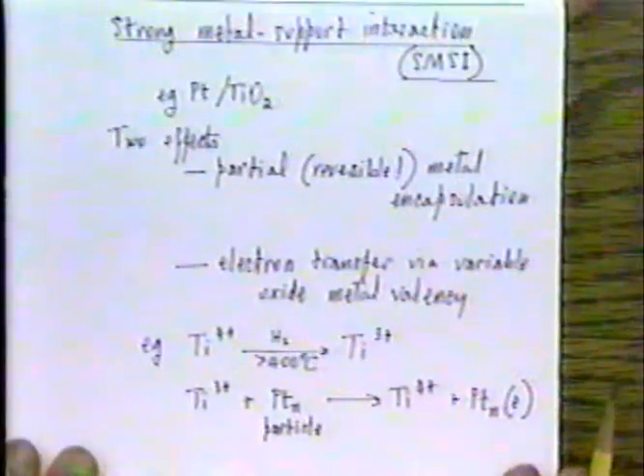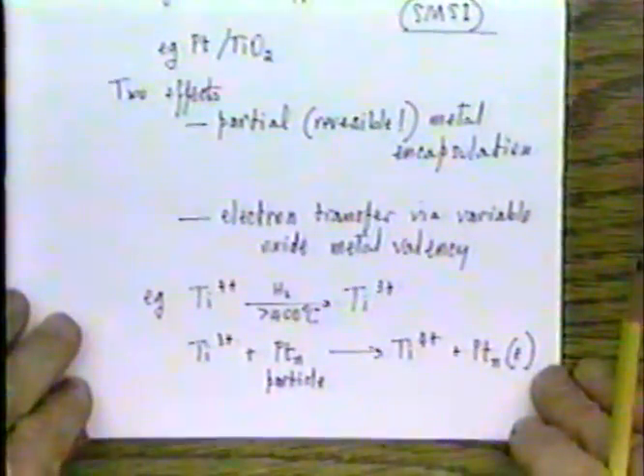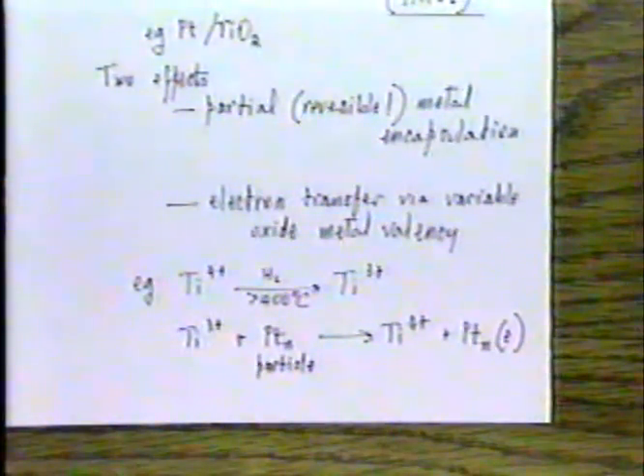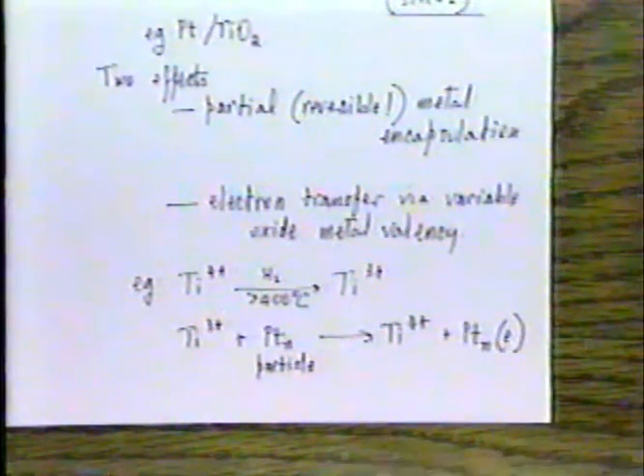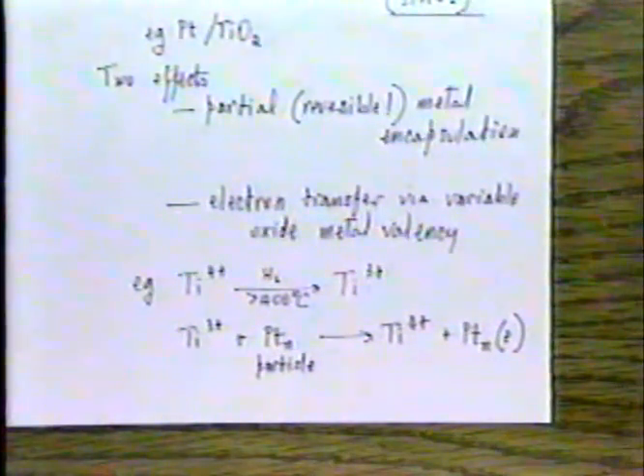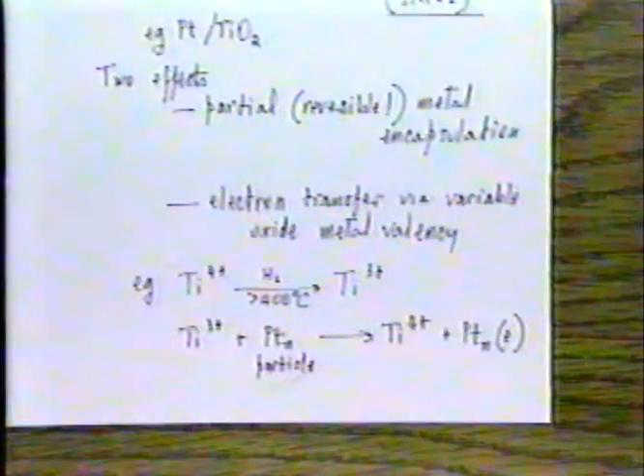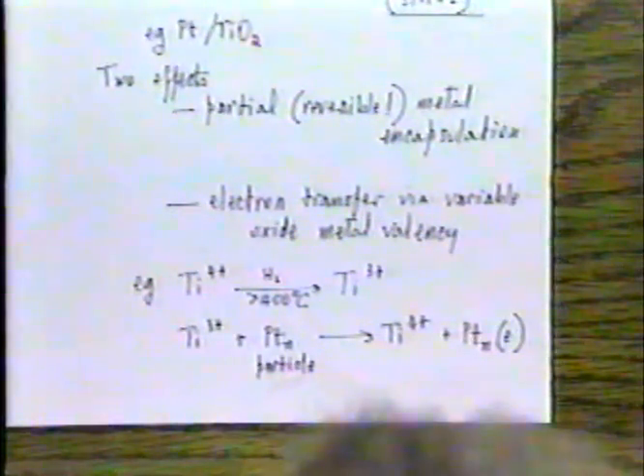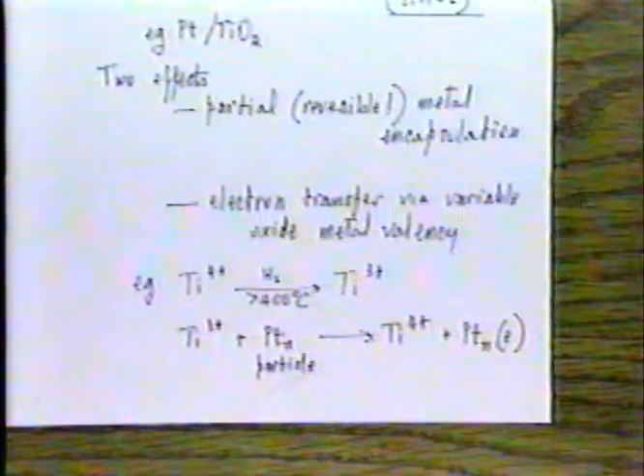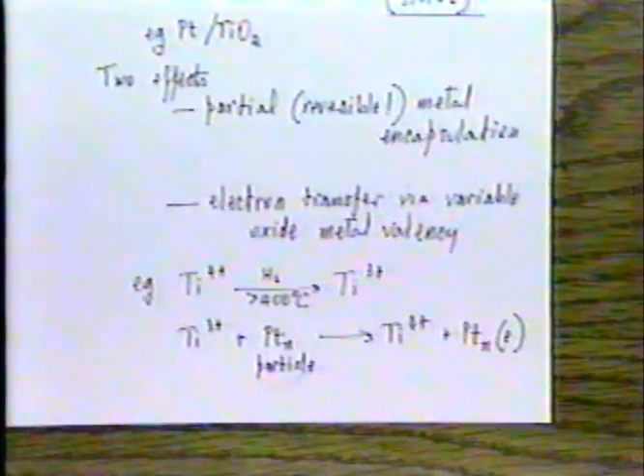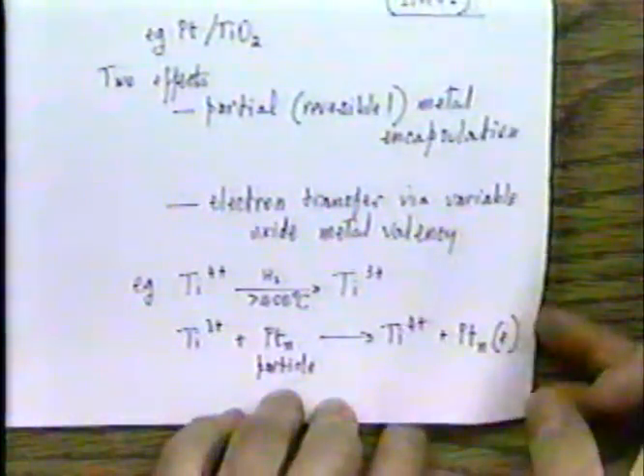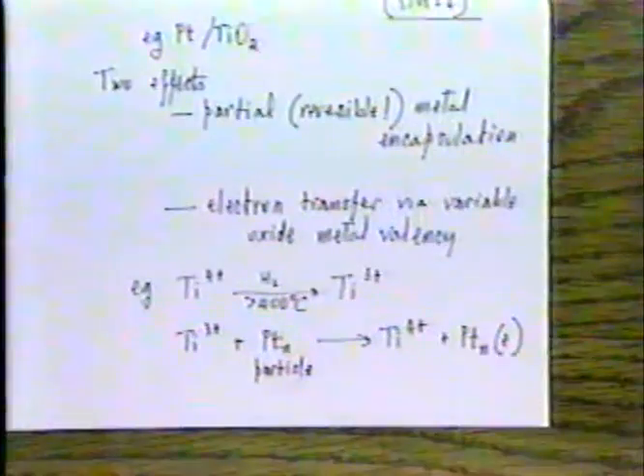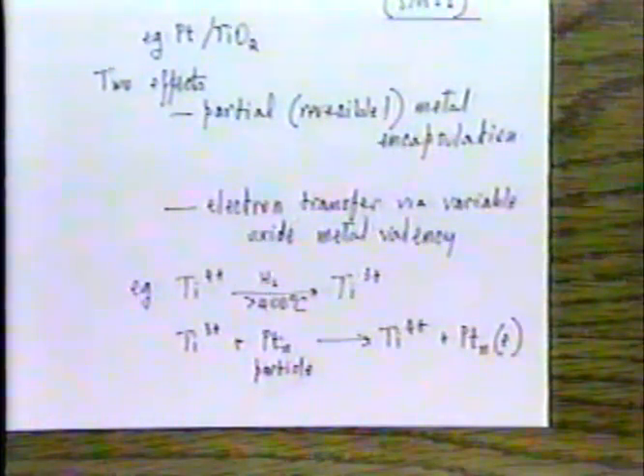However, there is very likely an actual electron transfer effect taking place at the same time, and this is summarized in those two equations at the bottom of the sheet. That is to say, under reducing conditions, some of the Ti4+ is reduced to Ti3+, and the Ti3+ functions as an electron sink in relation to the platinum particle which is sitting on the surface. In effect, it can dump an electron back into the platinum particle. The platinum particle functions as an electron-rich particle, which tends to inhibit hydrogen chemisorption, and in fact has an effect also on the ability of a platinum particle in that situation to carry out other hydrocarbon reactions. I don't propose to say any more about it at this stage.